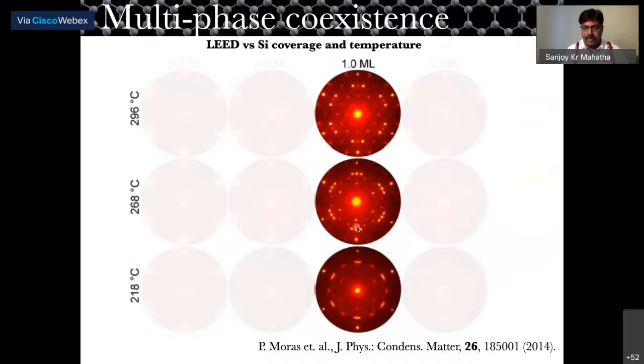And then as you increase the temperature, you see these spots are going away from the main 4 by 4, and here they are really far apart from each other. So this phase is 2 root 3 by 2 root 3. This is some kind of mixed 2 root 3 by 2 root 3 and root 13 by root 13, and this one is 4 by 4 plus root 13 by root 13.